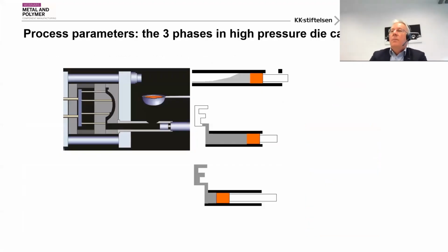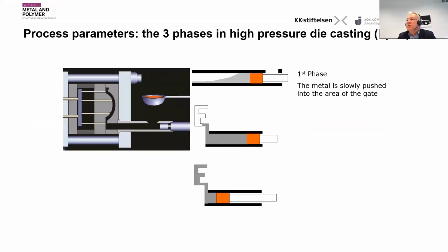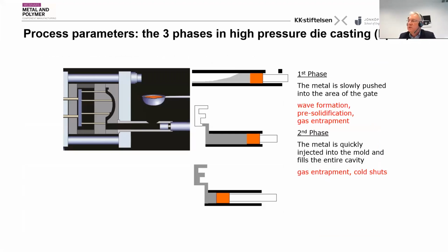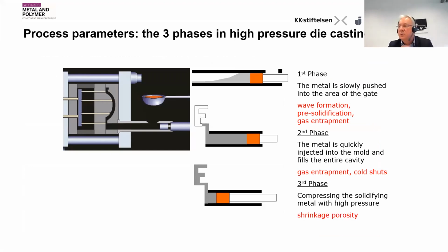Okay. But now we come to the 3 phases. In the first phase, the metal is put slowly to the gate. And there we have wave formation, pre-solidification. A lot of problems can evolve. Second phase, where we have the metal shot into the cavity, very short fill times, 30 to 50, maybe 70, 80 milliseconds. And then we have the third stage, where we can get shrinkage porosity. We apply a lot of pressure just in order to feed and have no porosity due to shrinkage in the part itself.